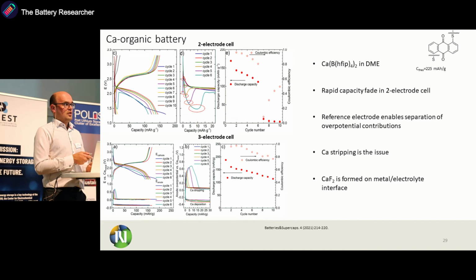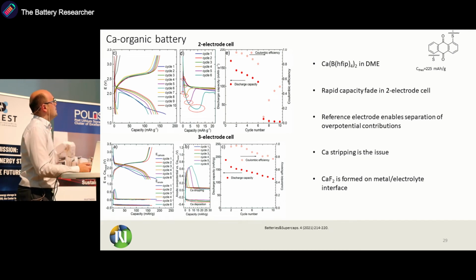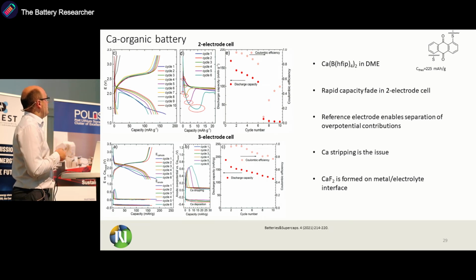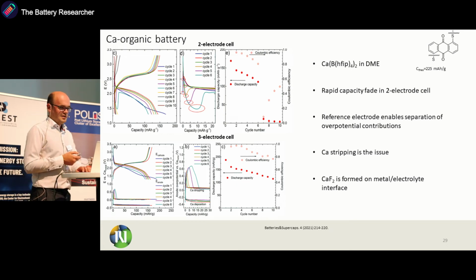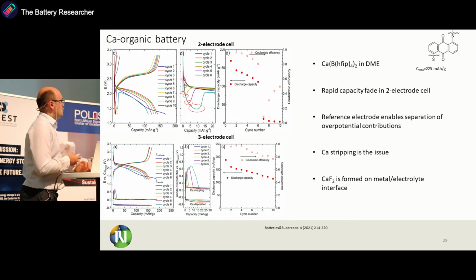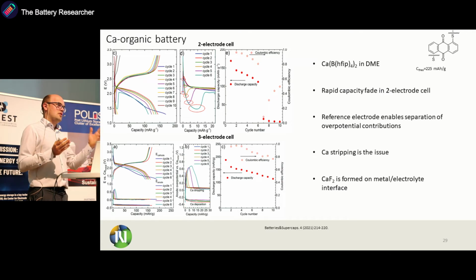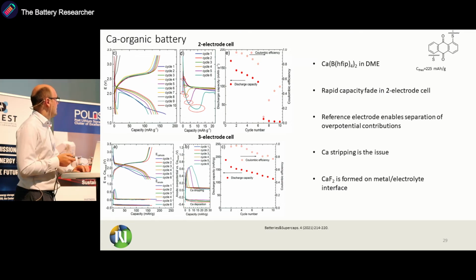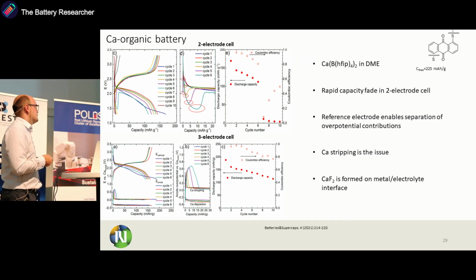So we applied the same polymer also to calcium organic battery with this electrolyte, which is developed here. And we saw, like it was shown before, that we have rapid capacity fade. So basically, after 6 cycles, the cell is completely dead, and we have no more cycling. To somehow explain this, we decided to apply a 3 electrode cell to separate the contributions of the anode and the cathode. And this was actually quite nice because we saw that there is no significant increase in the polarization in the performance of the cathode.